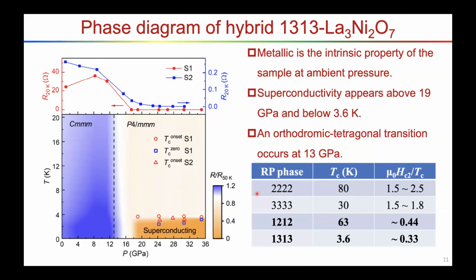It's very interesting if we compare the upper critical field, this HC2 over TC. For this bilayer phase, it's at this value more than 1. For the trilayer phase, it's also more than 1. But for this 1212 phase and the 1313 phase, this value is only half or below half. That means the superconductivity for the hybrid phase is very fragile, and